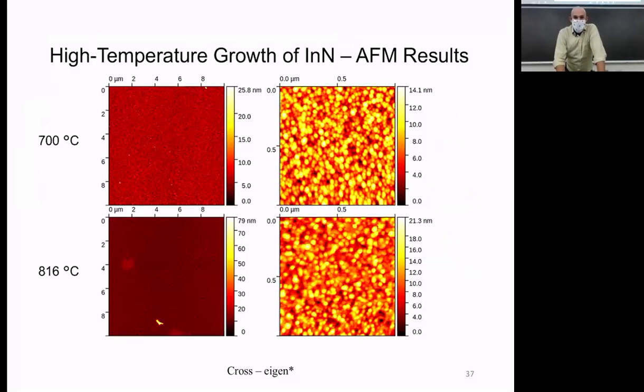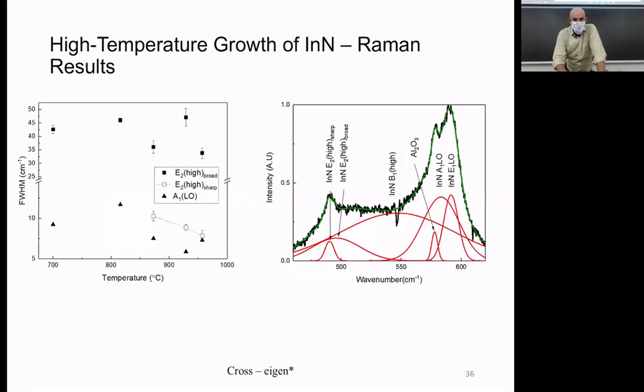I took the AFM and I went to go look at the AFM, and I got this mess. This doesn't look good. You guys remember what I said I wanted my semiconductor to look like? Nice and flat, no pinholes, lots of steps. I don't see flat, I don't see pinholes, which is okay, I guess, but I don't see flat either, and I don't see those steps. We're producing what look to be indium nitride clusters or something on our surface. And we're sure it's indium nitride because we do have the Raman results that show this indium nitride peak on them.